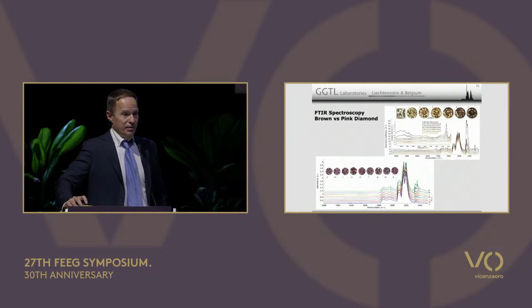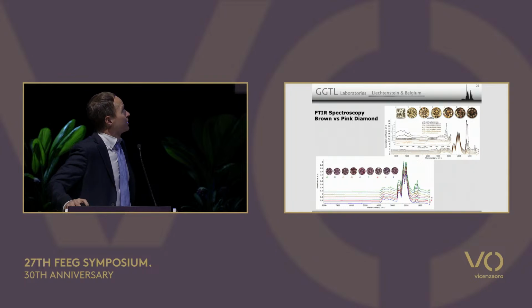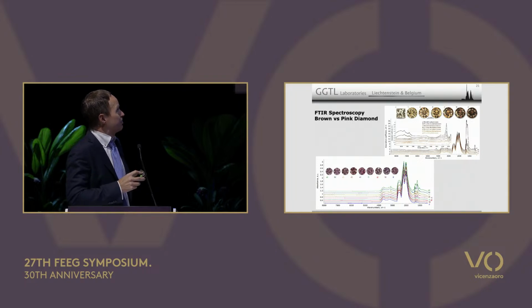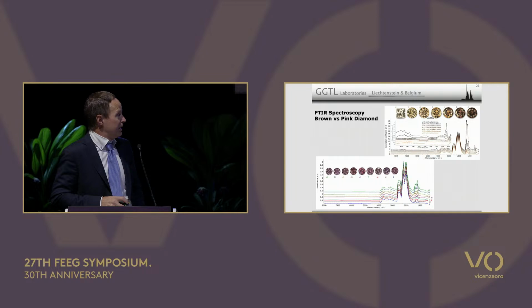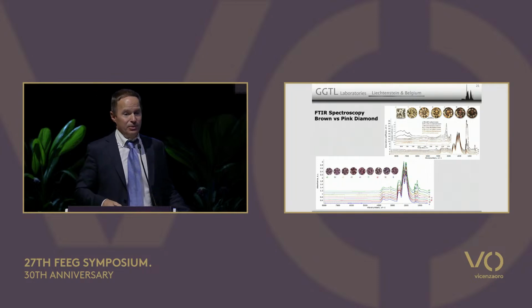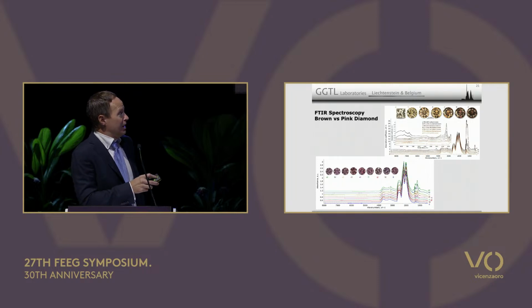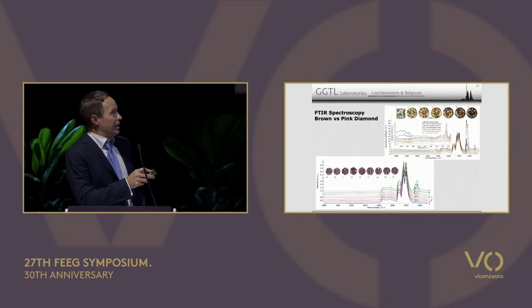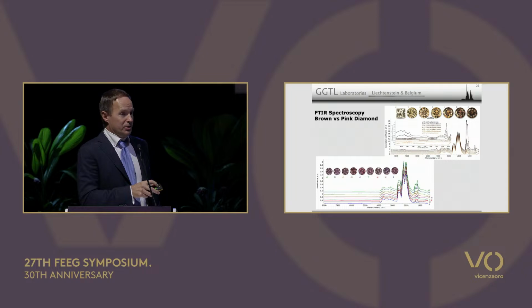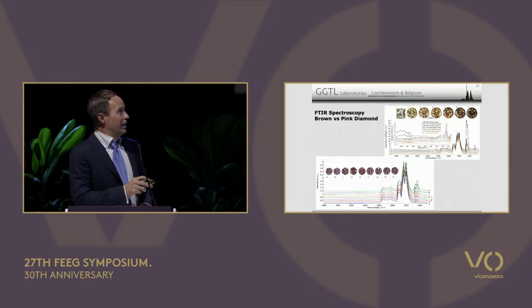Okay, let's have a look at some infrared spectra. So we have brown versus pink diamond infrared spectroscopy. You can clearly tell the two are not the same. So in brown diamonds, we have this region here, that is the near infrared domain. In the near infrared domain, in brown diamonds, in all stones that contain nitrogen, you will have a so-called amber center absorption. This absorption can be very strong and it can be very weak.